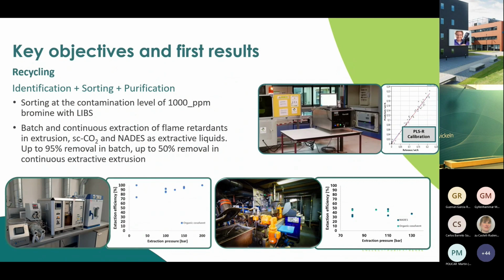And therefore, we set up a LIBS system, so laser-induced breakdown spectroscopy, with which we were able to identify the brominated content of the flame retardants up to 1000 ppm by using this LIBS sorting system, and able to sort: okay, this is a waste stream that does contain the brominated flame retardant and needs to go to the purification step, and the other waste streams can directly go into the mechanical recycling.